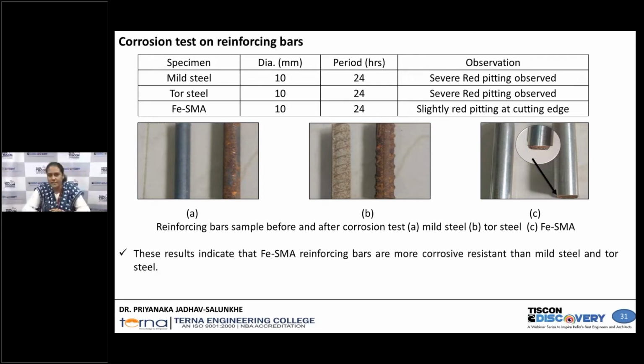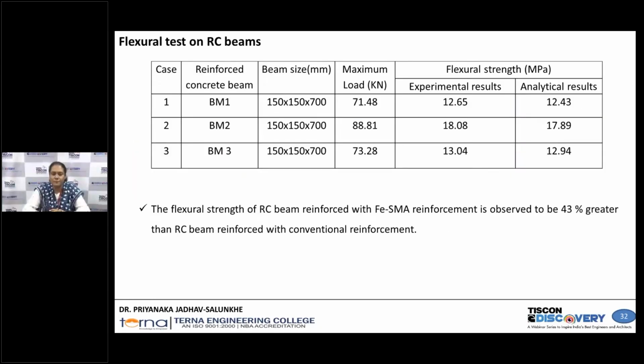Now let's see. As I discussed, we carried out the testing on the RC beam for flexure. The flexural strength we received for BM2, the RC beam with SMA reinforcement, is 43% greater than the RC beam with conventional reinforcement. So we can say, if we use a smart material, for example shape memory alloy, in a reinforced concrete structure, it enhances the corrosion resistivity, plus it increases the strength of that particular structure.